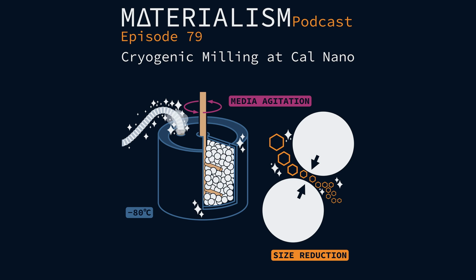I've actually seen X-ray diffraction studies where the whole point of the study was to show that X-ray diffraction is quantitative. It can give you phase fractions. And the case study that they showed was on milling time. They took whatever material they were milling, but they added, I think it was alumina media, and they showed that the alumina peaks, at 1 hour versus 10 hours versus a week, are just climbing. Like the volume fraction of that milling media, which is also getting ground up, is showing up in your sample.